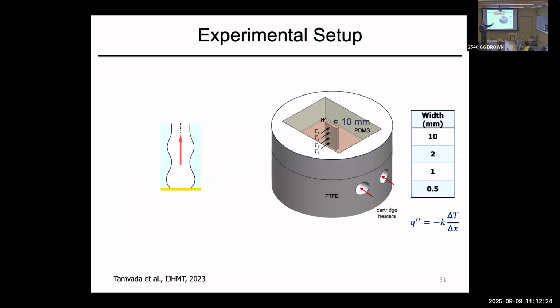So keep reducing the width of the heater such that there's just one liquid going up, one gas going up, and liquid coming from the side, right? Let's do that. The length of this heater is 10 millimeter. So we went from the 10 by 10 that people do to 2, to 1, to 0.5. I will tell you why we took 2, 1, and 0.5.